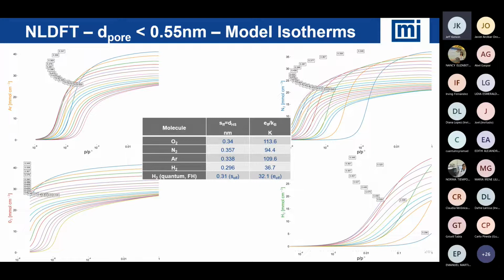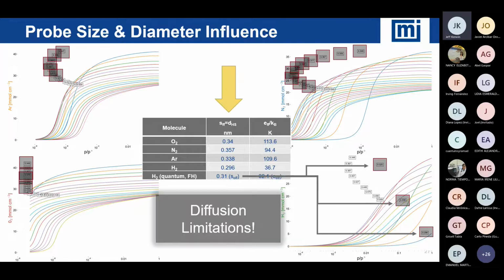Okay, I apologize. This slide is quite complicated. It tells a very interesting story, so we'll try to focus on the really interesting pieces of this slide. In each plot, those are the models for different gases. So in the upper left is argon, down below it oxygen, upper right nitrogen, down below it hydrogen. This is how those gases would adsorb in a cylindrical pore. And I have it narrowed, so I'm only showing adsorption in the very small ultramicroporous ranges. Okay. As we look at these, we've got to be very conscious of size.